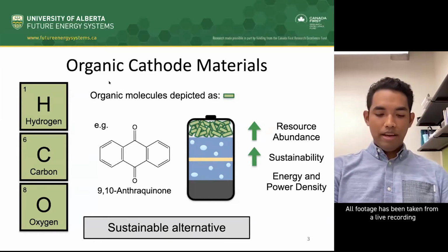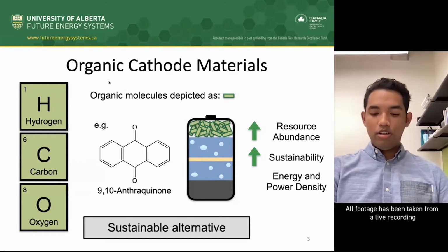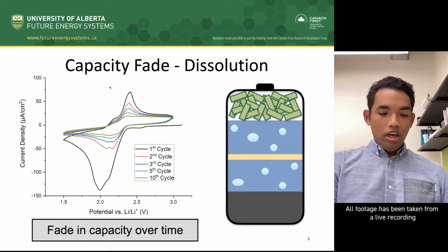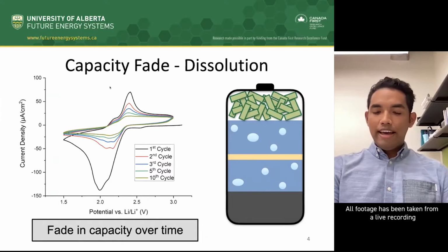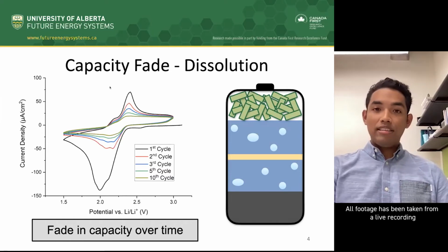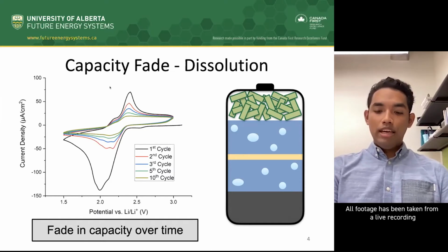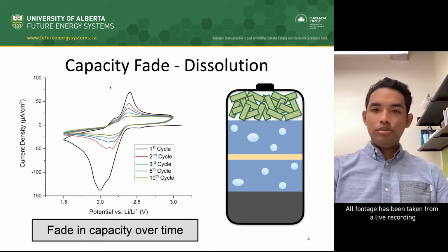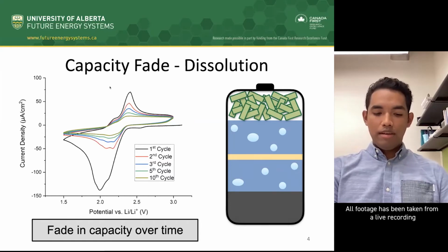Aside from the sustainability benefits, organic cathode materials may also provide improved performance, resulting from higher theoretical energy and power densities. While I have highlighted many advantages of organic cathode materials, there are some major drawbacks. The target of my research is to tackle the issue of capacity fade caused by active material dissolution. In layman's terms, this means that the material used to store the lithium is lost over time as it dissolves into the liquid electrolyte, resulting in a loss or fade in the battery's capacity.